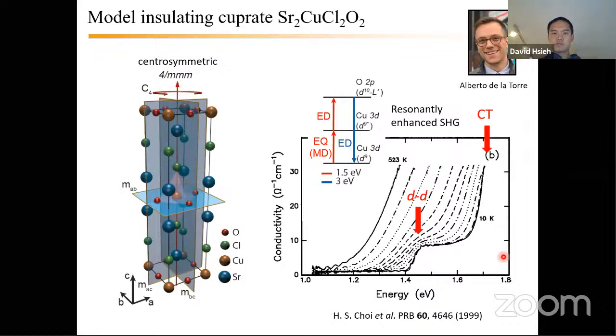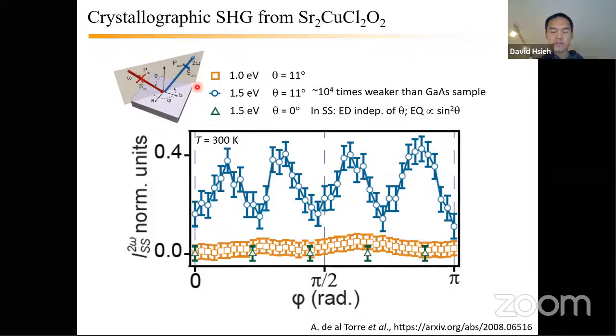Okay, so just to hammer that point home a little bit more strongly, 1.5 eV incident photon energy is where we think this resonant enhancement is achieved. So if you look at the data, here's 1.5 eV data at oblique incidence, shown by this blue curve here. As I mentioned, the data is really weak, but under the same experimental conditions, if we looked at a gallium arsenide wafer, this is about 10,000 times weaker. So it's a bit noisy for that reason. But nevertheless, you can pick up a clear RA type behavior.